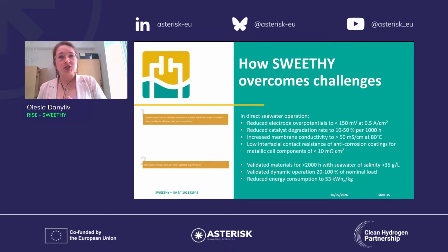Another objective is that we will develop and test a short and scalable half-kilowatt ion exchange membrane stack. For that, we define the key performance indicator that we will need to validate the developed materials in the stack during more than 2,000 hours with direct seawater that has high salinity, more than 35 grams per liter of salts. Then we also need to validate it with dynamic operation, because we are looking at how to work with intermittent conditions coupled to renewable sources of energy.